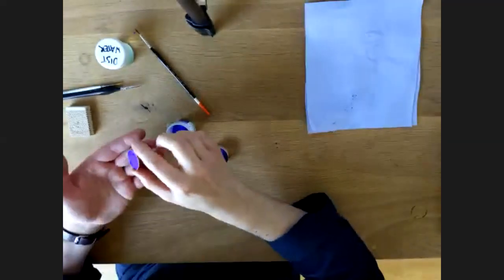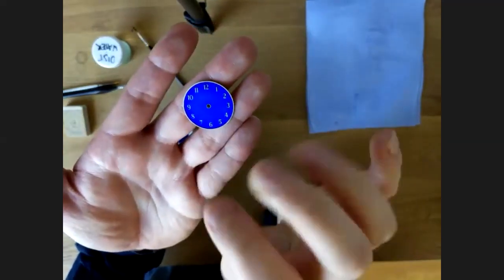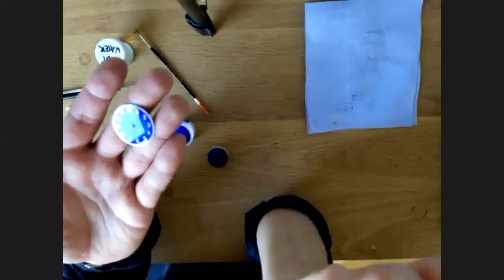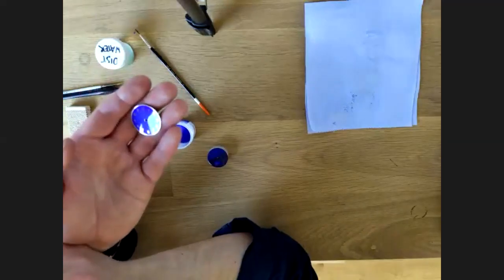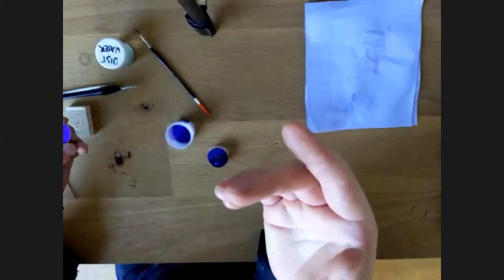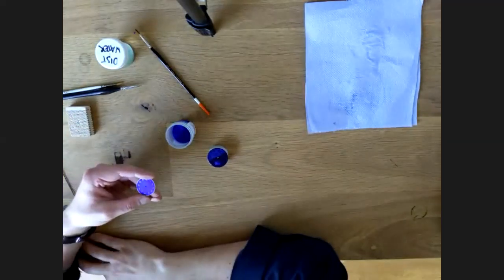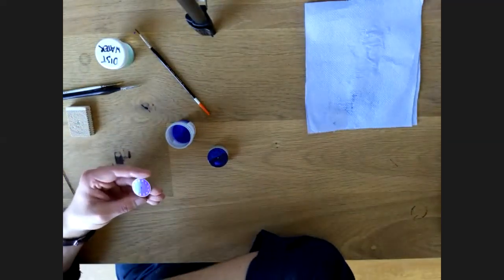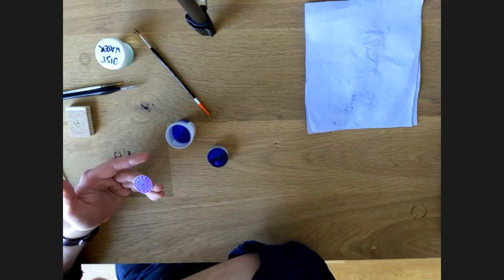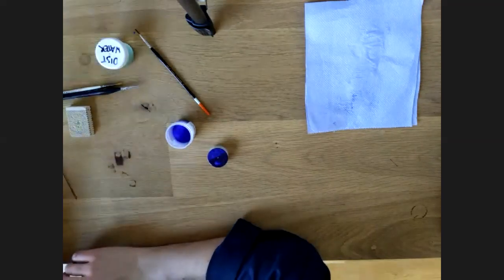But you have issues with, like I was talking about, expansion and contraction. You've created all these little cells, like inside the 6 and the zeros. The silver and the enamel want to expand and contract at different rates, so you end up with tiny hairline cracks if you don't have it right. We had to work with our die maker to get the right draft angles and the right thickness of wall, all these things that on paper or in your mind are going to be fine. Also finding the right enamel that's hard enough to hold it, but not so hard that it causes it to warp. These are the kinds of things we're playing with and trying to work out.